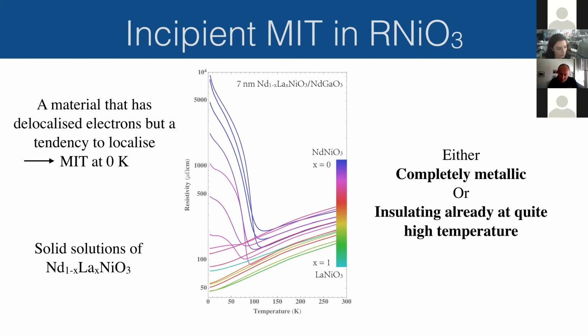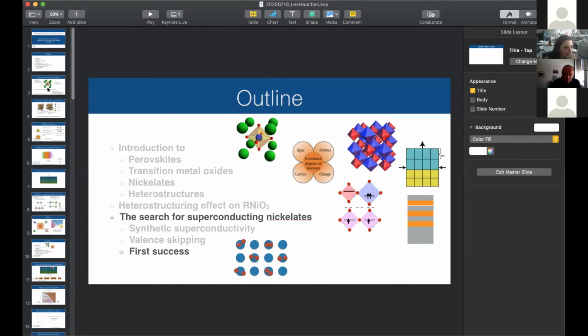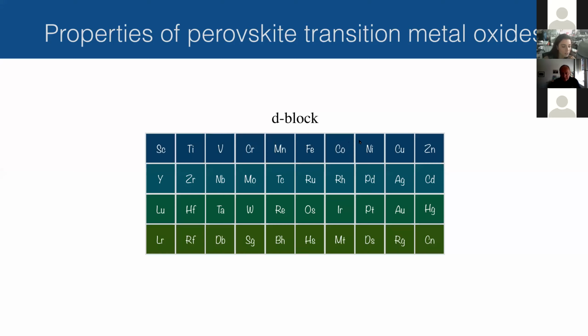Yeah, I see why you ask. So lanthanum titanate is a Mott insulator, I'm sure you know, whereas the nickelates are called negative charge transfer insulators. If you look at the periodic table, in fact, I can probably just show my slide with the transition metals. Here, titanium is really far on the left of the periodic table, whereas nickel is really far on the right. So actually they have quite different behaviors, even though this has one 3d electron and this has one EG electron.